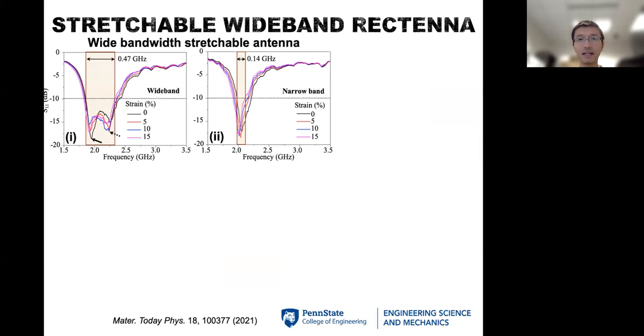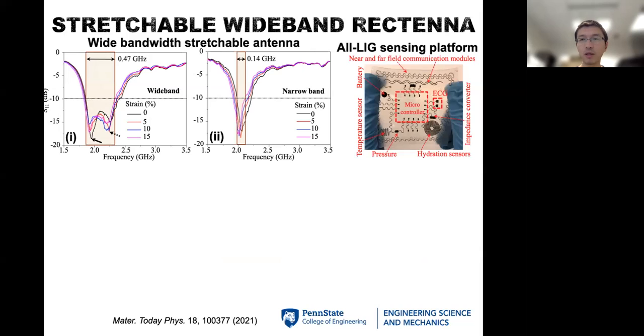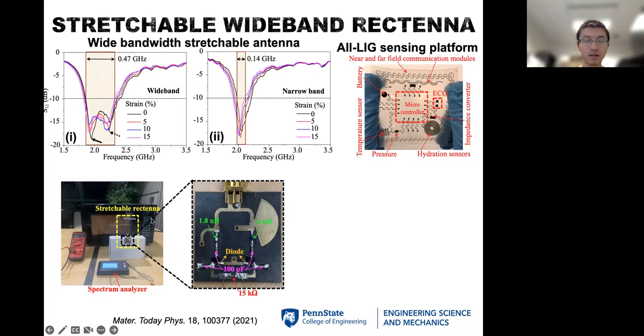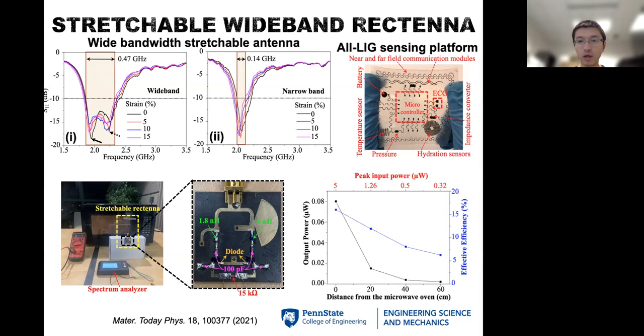And further, we can design the antenna to not only operate stably, but also have a very wide band, because energy combined together over this band can be integrated to further enhance the energy conversion efficiency. So this is the simple demonstration of the radio frequency antenna combined with the other devices. And we have combined that energy to go through the rectifier and then get it into DC power. And this is a quick demonstration with the energy emitted from a microwave oven. So it's ultra small. The input power is probably around 1 microwatt. And this is much lower than the other energy sources, but we were able to harvest energy at an efficiency of about 5 to 10%.